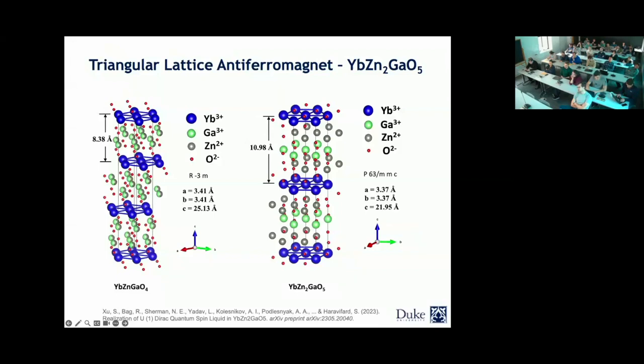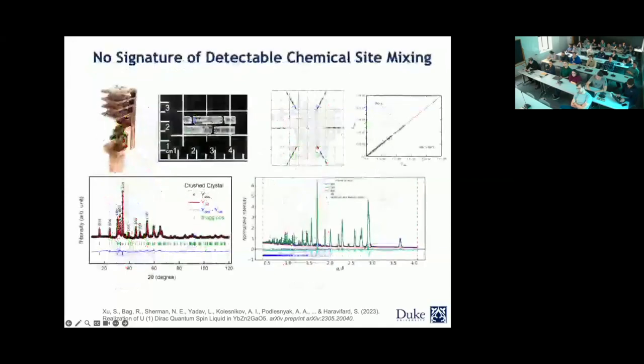We attempted this, but of course we need to make sure that it really doesn't have chemical disorder. Here I'm showing you the single crystal we were able to grow back at Duke. You can see that it's very transparent, so it has very high quality. This is a Laue pattern for it, which again shows that it's a high quality single crystal. Then we did powder XRD on a crushed single crystal. We were able to fit the pattern with a new structure with no chemical disorder, and the fitting worked really well.